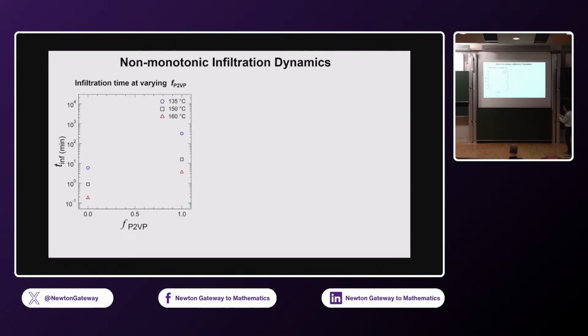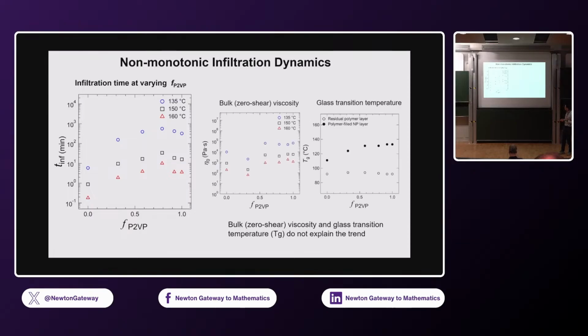So this is a very sticky polymer, all P2VP, and this is polystyrene, not very sticky. And let's see what happens in between. So this is the time it takes to fully infiltrate my particle packing. Do you want to see what the result is, or should I go to the conclusion? Okay, so we see this non-monotonic behavior. And we try to see, is it the bulk viscosity that is doing this? Because bulk viscosity doesn't change a whole lot. Glass transition does change a little bit, but it really doesn't explain this up and down trend that we are seeing. So this is still a big mystery to us. I think there are a lot of people that could advise us on what might be happening. So I'd love to hear your thoughts on this.